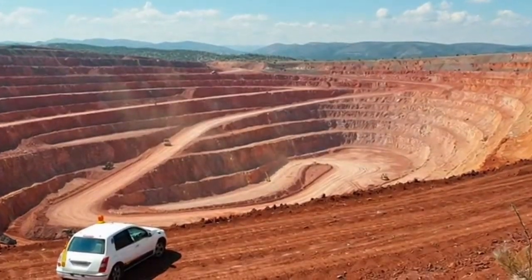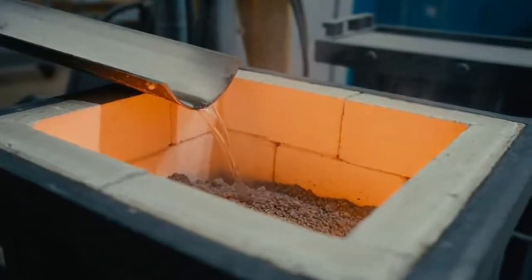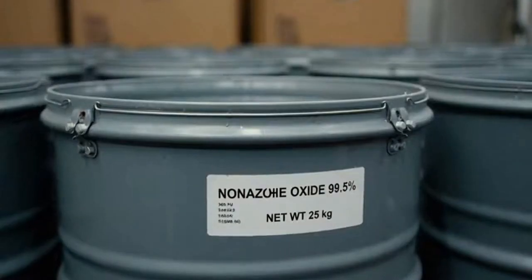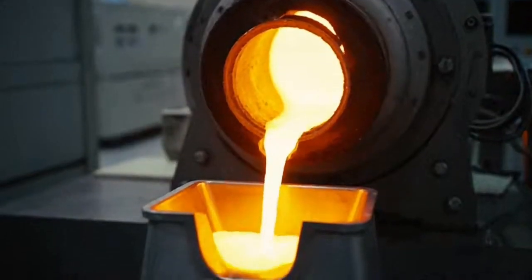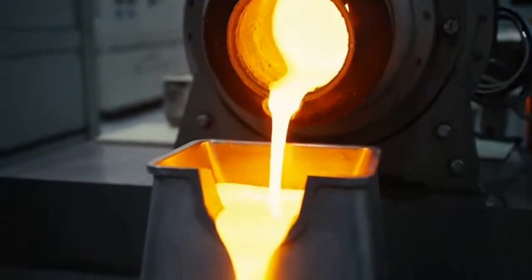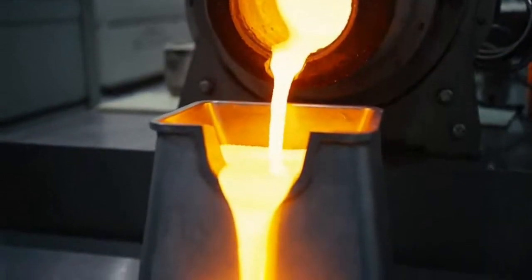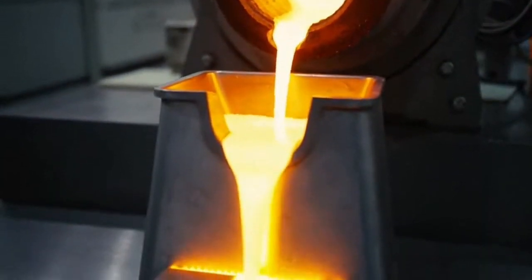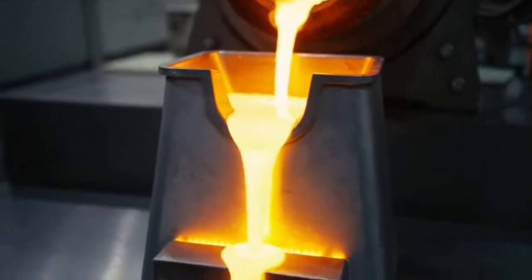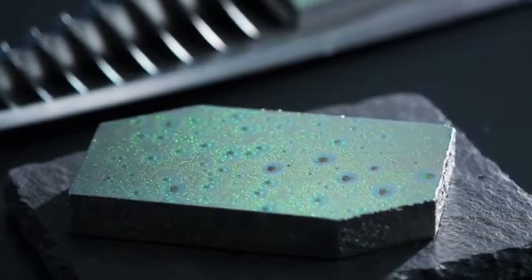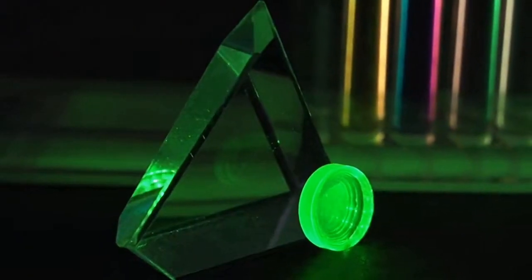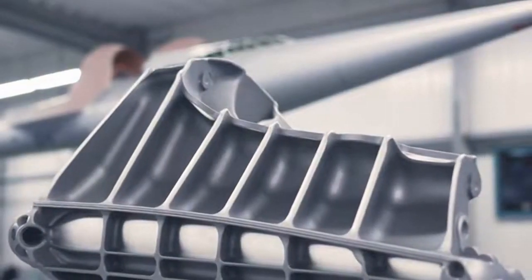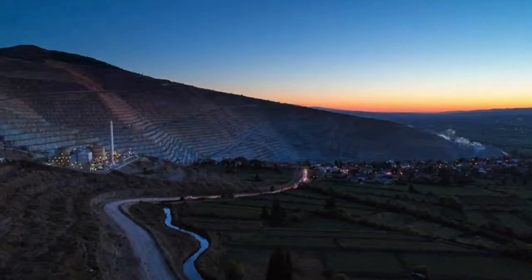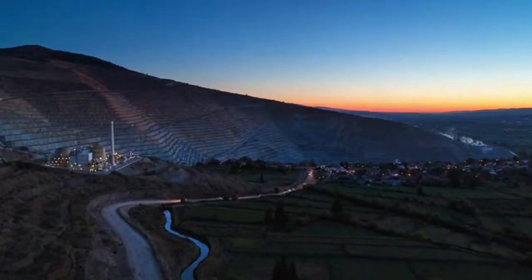The goal is rare earths in solution and troublemakers in their own lanes. Iron should stay polite, aluminum should not foul everything it touches, calcium and magnesium, the classic freeloaders, should be managed so they do not co-precipitate when you start to change pH. Then you invite the rare earths into the organic phase. The usual hosts have long names that sound like a chemistry quiz. Di-2-ethylhexyl phosphoric acid is a workhorse, and they have a simple job, to prefer lanthanides over most other cations when the acidity is just so.